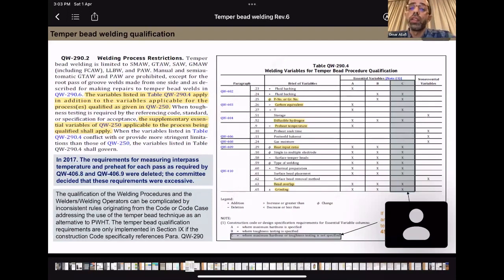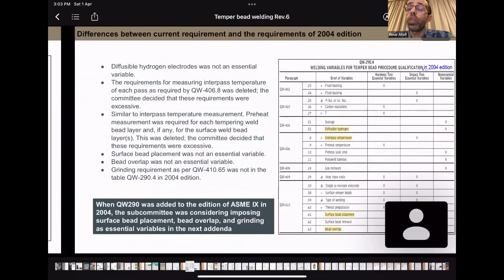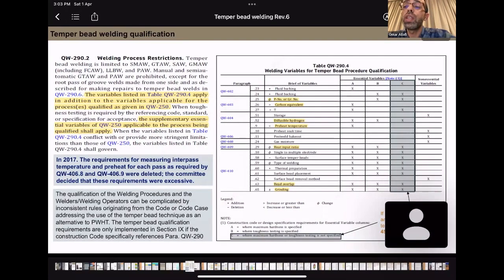One note I would like to mention here is that in 2004, when it was adopted by Section 9, there were two essential variables required, which are the interpass temperature between each layer and the preheat temperature of each layer. So these were essential variables in 2004. These requirements of measuring the interpass temperature and preheat temperature for each pass were deleted in 2017. And when I searched into why, they said they were excessive, but the interpass temperature is still an essential variable. When we refer to different codes, we'll see that the interpass temperature is required to be controlled.